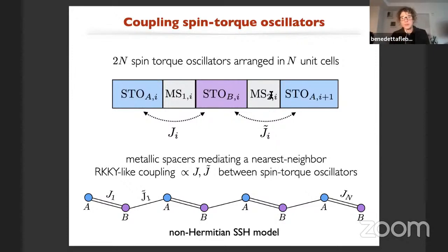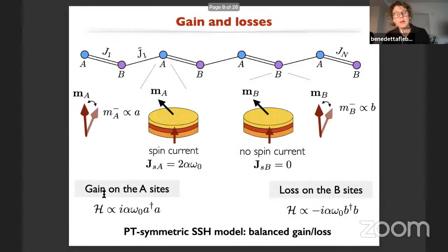And probably some of you can recognize in this a sort of SSH model. In our case, a non-Hermitian SSH model, in which we create this artificial system with two sublattices per unit cell. Our sublattices are the spin torque oscillators, and this J and J tilde are RKKY-like interactions mediated by some metallic spacer. Then we just need to control the spin injection, and this is the last thing that we need to do to achieve the system that we are trying to realize.